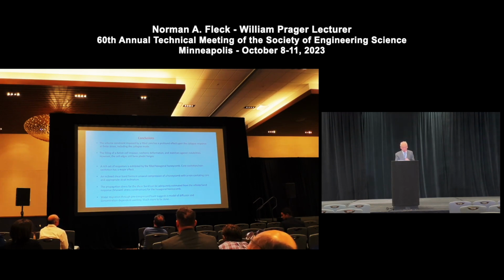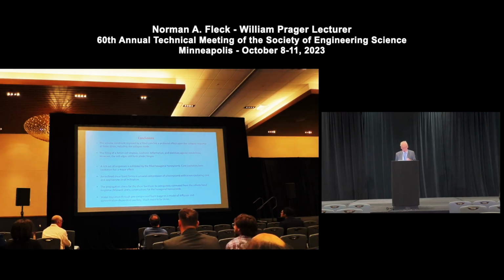I pointed out that in the non-cavitating case of constant volume, this feature can lead to strong instabilities. Inclined shear bands can form that can be analysed by a Maxwell construction, much as we did in the past for the case of fibre composites. There is much to be done, I think, particularly in this interesting world of diffusion or migration by whatever motion. It may be capillary rather than diffusion, but this motion of liquids through the structure, and then once the liquid gets to the interface, a reaction taking place, leading to the propagation of an actuation wave through the structure. And on that note, I'll finish. Thank you for your time.